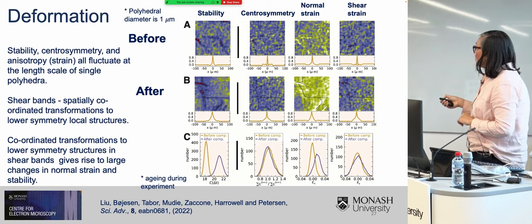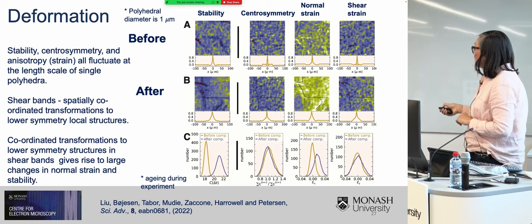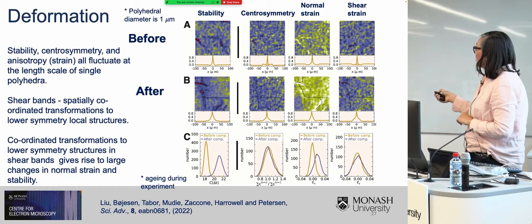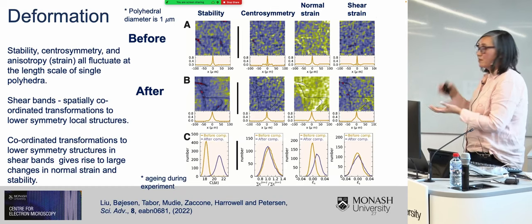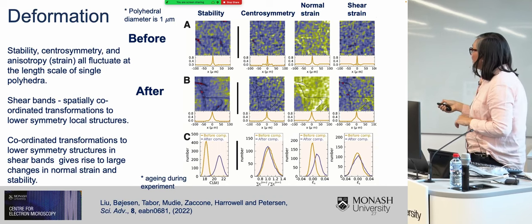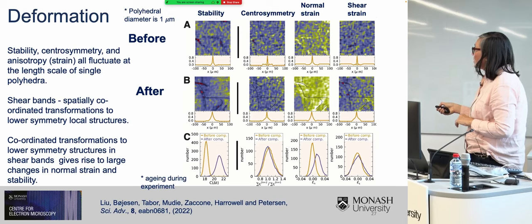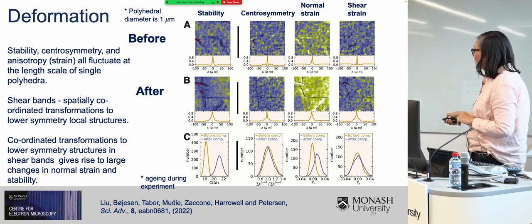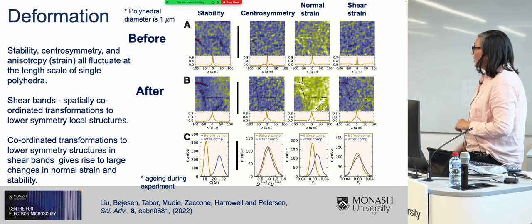So in this column here, I'm mapping the local stability of my glass. In this column is the local centrosymmetry. Here is the normal strain and here is the shear strain. This is the glass before deformation and this is the glass after I've compressed it. Under each map is the radially averaged autocorrelation function that shows you the extent of any correlations in the map. And then down the bottom here are histograms that show you the distribution of values from each one of these maps. So I'll just set a scale for you here.